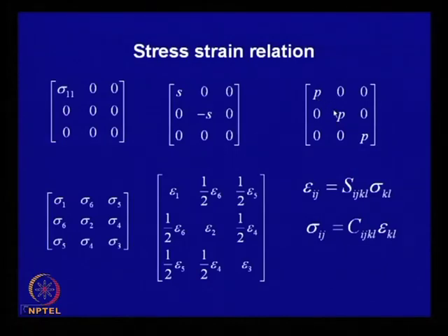If it is minus P minus P minus P, that means you are compressing a solid from all directions. This hydrostatic state of stress cannot cause any plastic deformation, because if you change the reference axis and try to find what kind of shear stress you have, you will find all the shear stress components are 0. If there is no shear stress, the material cannot undergo any plastic deformation.